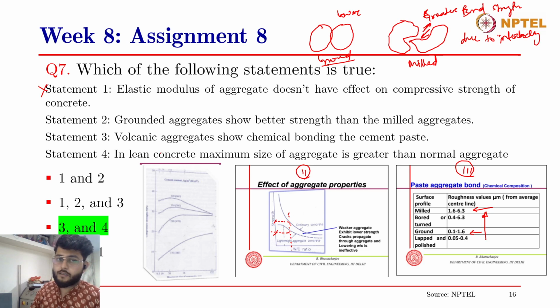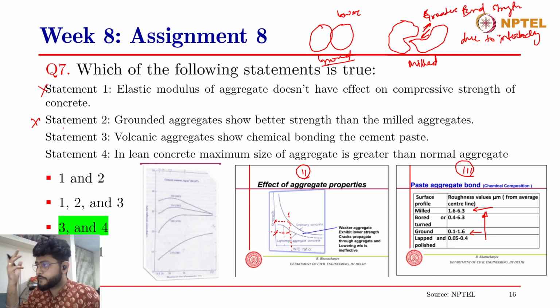So therefore, this statement is again wrong, because ground aggregates will show a lower strength than milled aggregates. Milled aggregates have an irregular shape, they have a higher surface roughness, and that surface roughness contributes to the interlocking force between these aggregates and in turn increases the bond strength between these aggregates. So statements 1 and 2 are wrong.